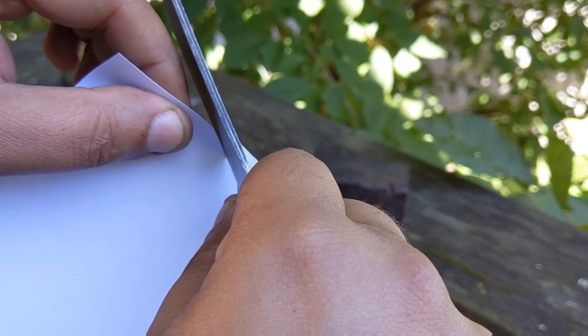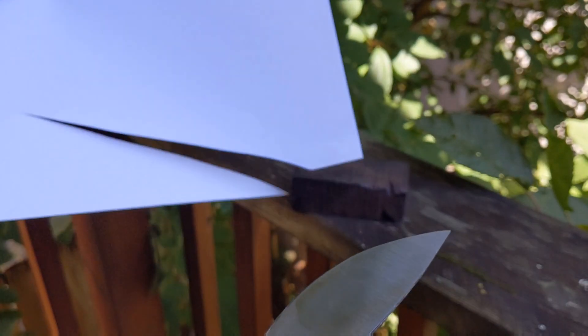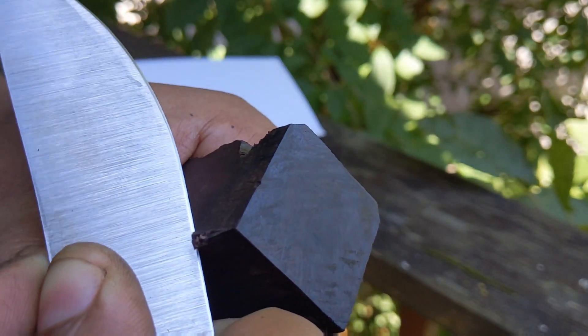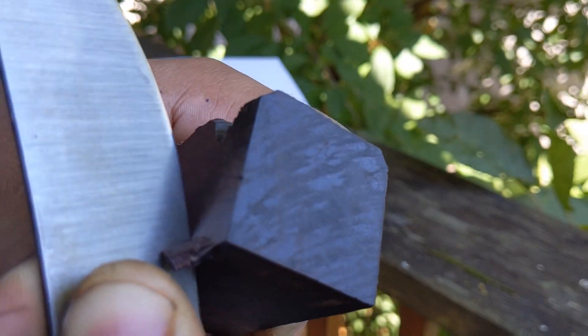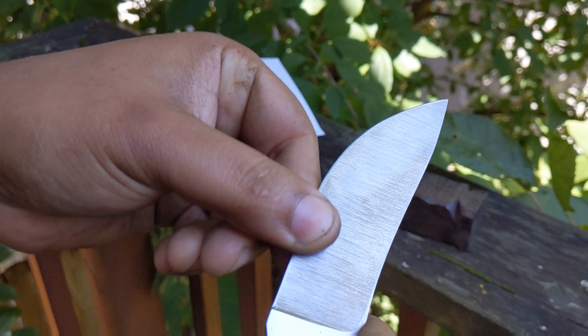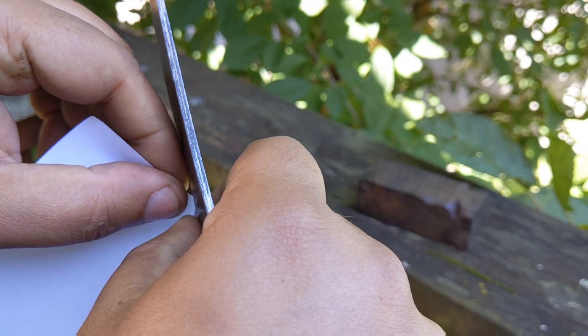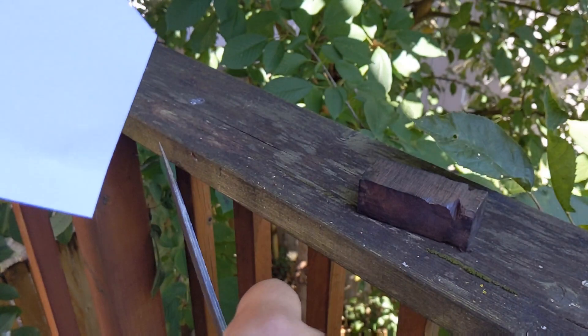What we're testing here is the edge stability of the steel. If you have a very keen eye, you can see we're able to have something this hard yet incredibly stable. That's one of the unique properties of 52100 — it has super fine carbides, only 6% carbide volume, M3C more complex iron carbide, chromium rich. What's fascinating is it's not the most aggressive edge or the longest cutting, but it offers extreme stability. Watch the cut — no chipping damage whatsoever despite that very gnarly African blackwood.